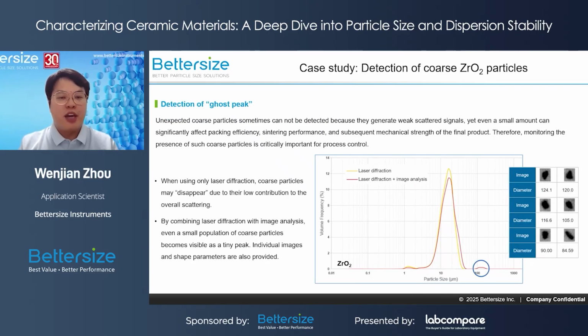Here is a real case that shows why it is important to detect unexpected particles. The sample here is zirconia powder, which we disperse in water for full dispersion. As mentioned earlier, even a small amount of abnormal coarse particles can significantly affect the final performance of the product. Let's focus on the particle size distribution curve.